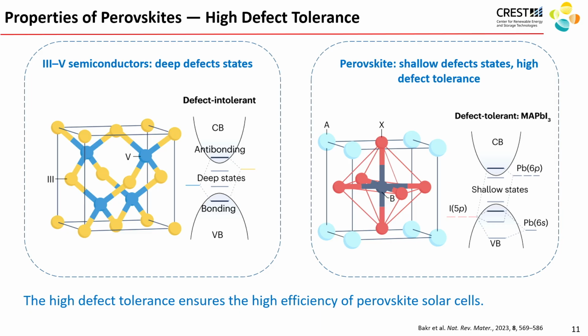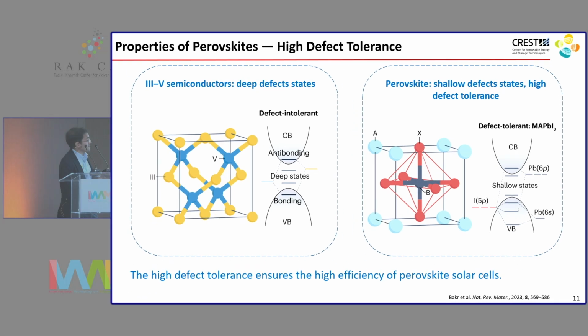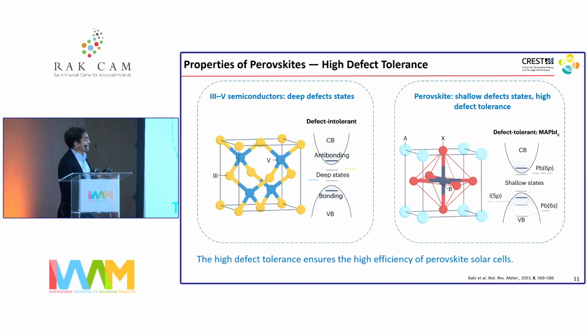What makes perovskites kind of unique from most other semiconductors, compound or silicon, is that in silicon-type semiconductors or other III-V semiconductors, because the conduction band and valence band are formed from bonding and anti-bonding states, whenever you have a defect where there are dangling bonds, a trap state forms within the band gap, and that leads to a deep trap state that tends to quickly deteriorate the electronic transport properties.